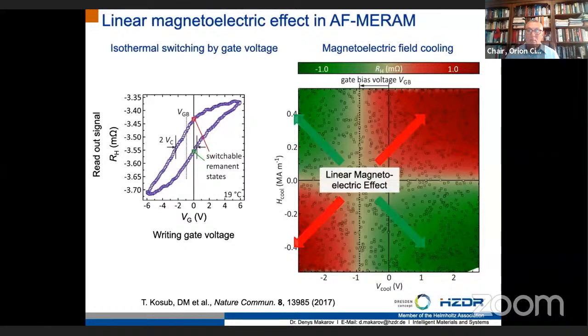Such magnetoelectric cooling allows you to set up the antiferromagnetic state, and this state now can be manipulated, for example, by electric voltage at constant temperature, so isothermally, without any need to modify the magnetic field, which contributes to the application potential of this memory concept. What you can see on the left-hand side is that for the specific conditions, also at room temperature, you can open the magnetoelectric hysteresis loop. You can get two remnant states, which allows you to record information in this thin film.